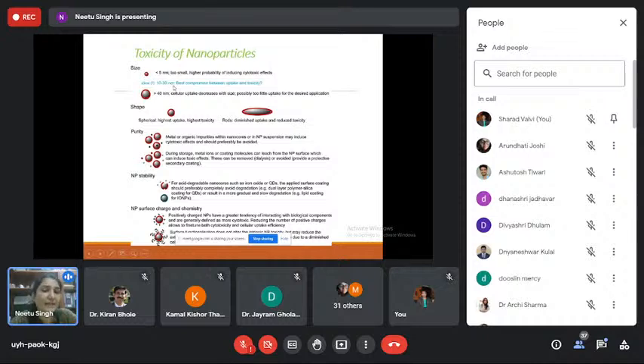So then what is the ideal size? It is understood that about 20 to 30 nanometers is something which is good for uptake, but then the toxicity will not be that much. If you have a shape argument, spherical nanoparticles have the highest uptake. However, they also have very high toxicity because they can easily interact with the cell membrane. Whereas if you have a rod, depending on what the aspect ratio of this rod is, it's an anisotropic structure, right? So depending on the aspect ratio, let's say it is a few nanometers thin in this dimension, and a few hundreds of nanometers long, right? Larger particles will just sit there, so the toxicity is reduced.